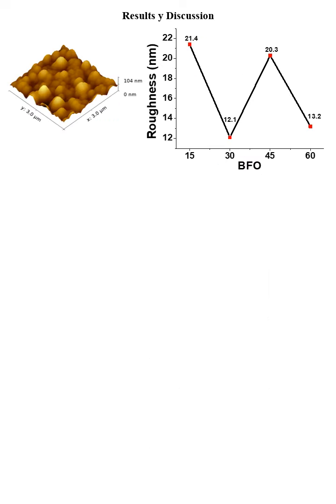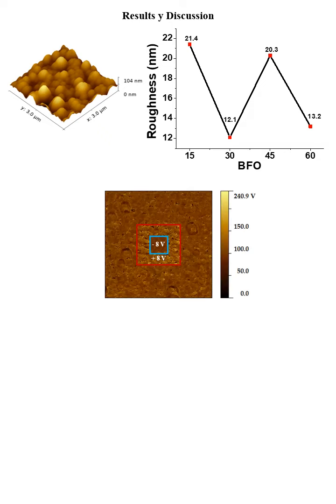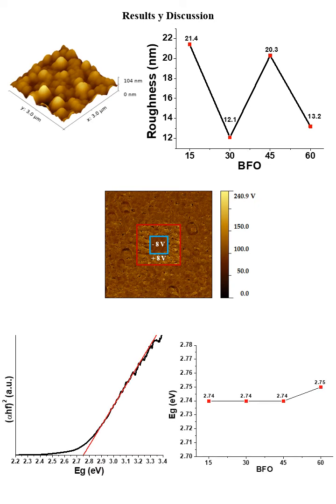Atomic force microscopy revealed the roughness of the thin films, which were between the values of 21.4 and 12.1 nanometers. The behavior of ferroelectric domains was observed through piezo-response force microscopy, where the films were written through the application of 8 volts with different polarizations, indicating not only the presence of ferroelectric domains but also their reorientation capacity through the influence of an external field.